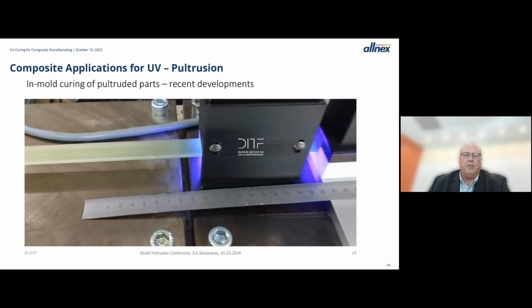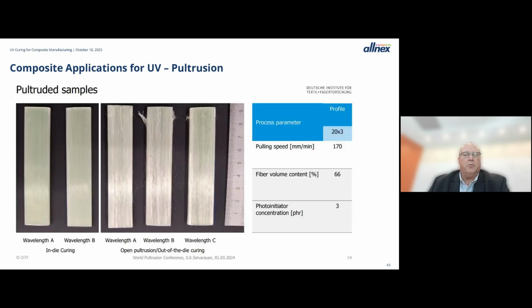And I mentioned that most of the time things are open mold, but here's an example of some people doing some work where they have the UV in mold, and you're curing in the mold while the part is being pultruded, and the effect that has is pretty evident here. On the left side, you have in-die curing. Those parts are nice, smooth, well collimated, and if you look on the right side, you see that these parts aren't as high quality if you're doing out-of-die curing. So while the majority of UV curing is done outside the mold, there's a lot of work being done to see what can be done to cure inside the mold and improve composite properties that way.